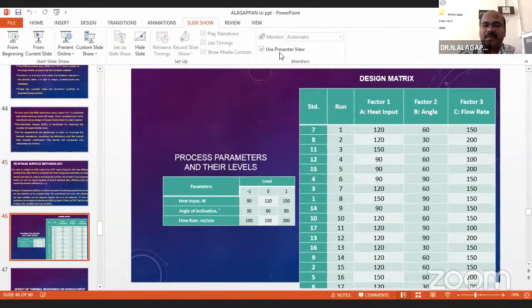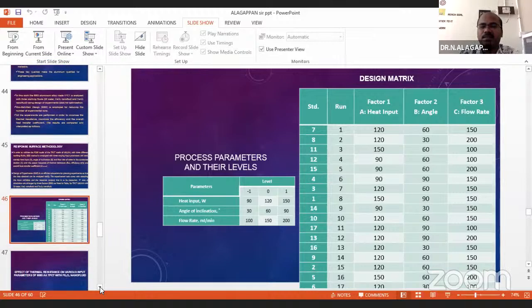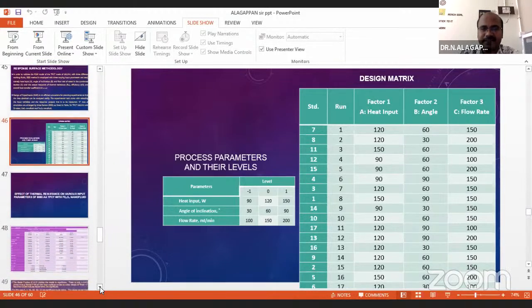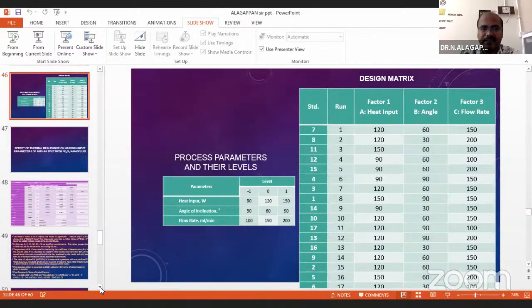So these are the input parameters I mentioned already, which are run by your design software. So -1, 0, 1. For the first factor, heat input, I am giving 90, 120, 150. And the angle of inclination I am selecting 30, 60, 90. The flow rate 100, 150, and 200. So these are the runs given by our normal strategy, but the standard run given by the software is like this.